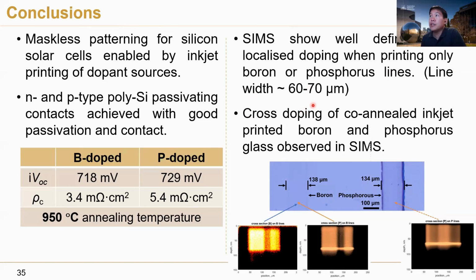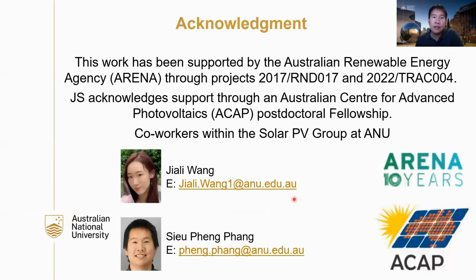But if we co-anneal a sample with both boron and phosphorus lines, we start seeing a contamination of phosphorus into the boron lines. And that's something that we're still working on. So that's the end of my talk.